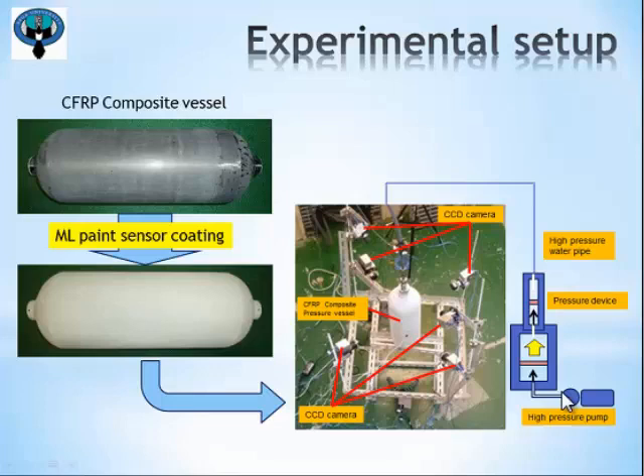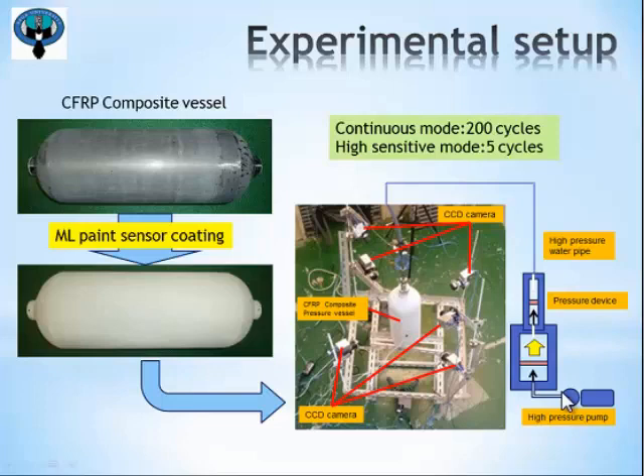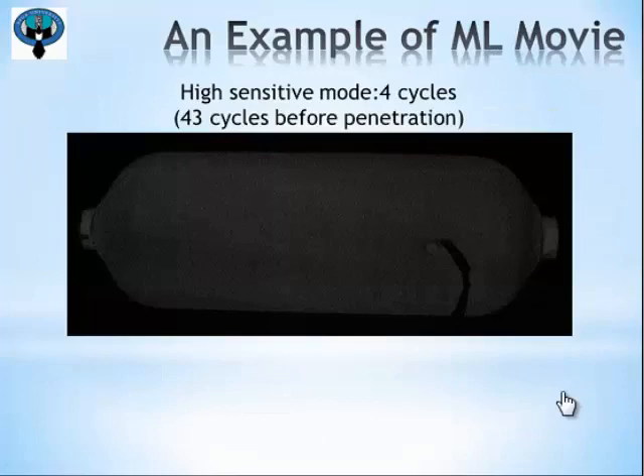The experiment was carried out repeatedly in a set of 2 experimental modes. One is continuous mode with 200 pressurization cycles, and another is high sensitivity mode with 5 cycles. In the latter mode, ML images with high signal noise ratio are obtained. And this movie shows an example of ML images observed in high sensitivity mode.